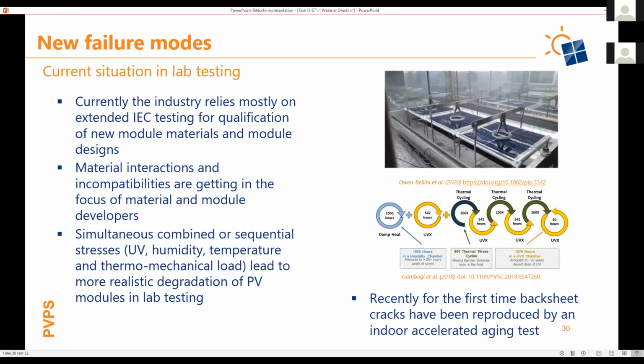And that's what's happening right now, and that's actually how industry adapts to this. So some years after these cracks first occurred, several research groups, especially in the US, went on this problem and tried to replicate this backsheet cracking. Two different groups - one from NREL with their combined accelerated stress test, and from DuPont with their sequential stress test - both succeeded in recreating these cracks after accelerated indoor testing.